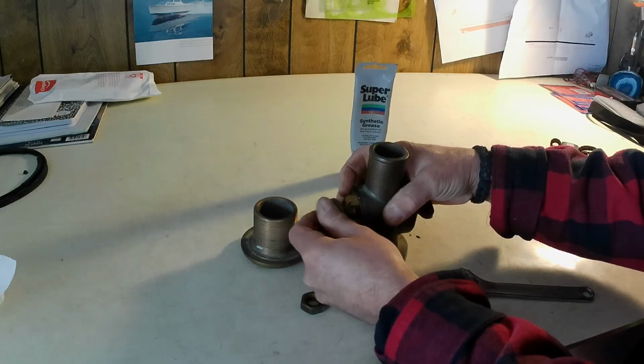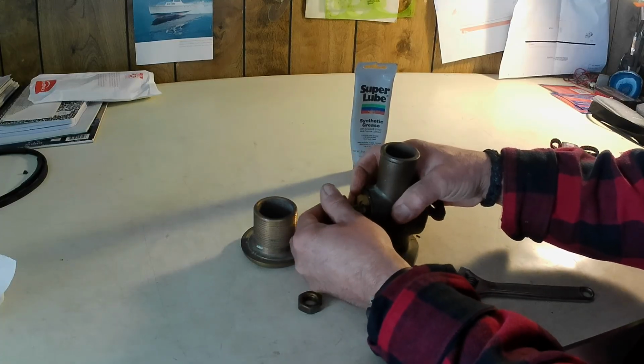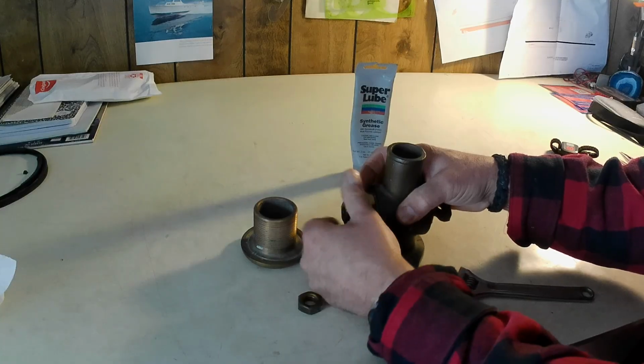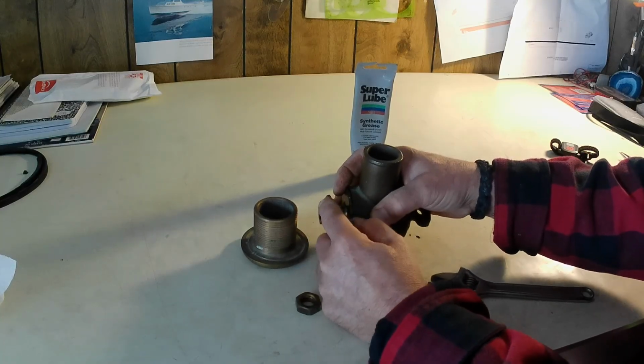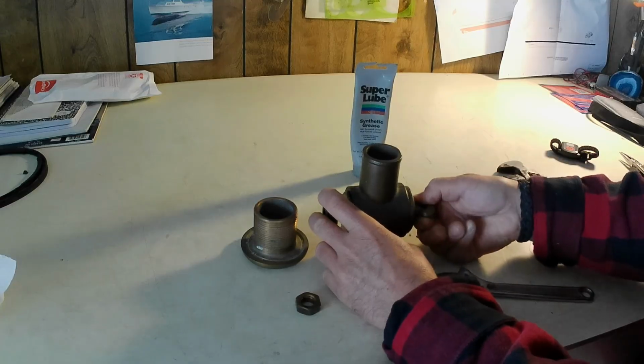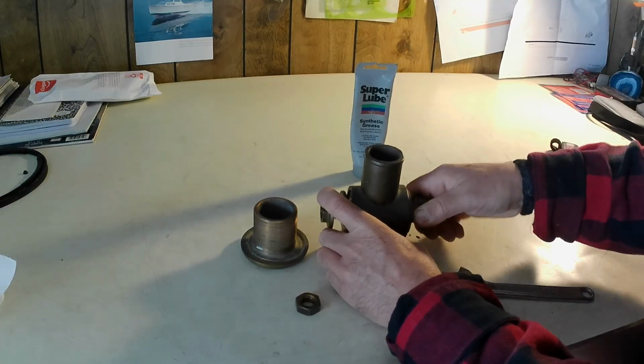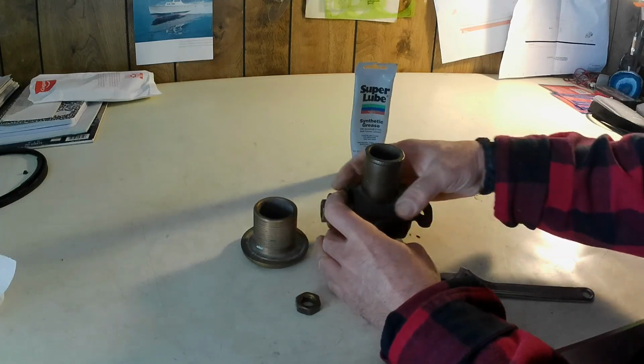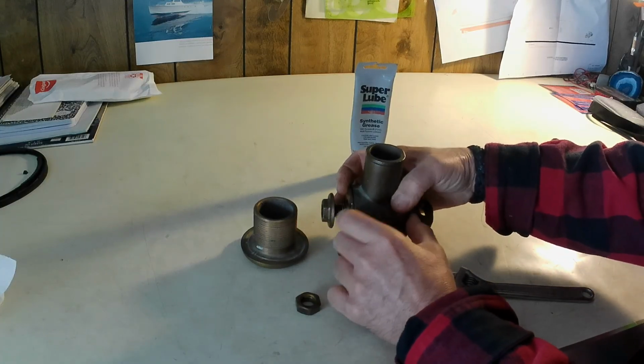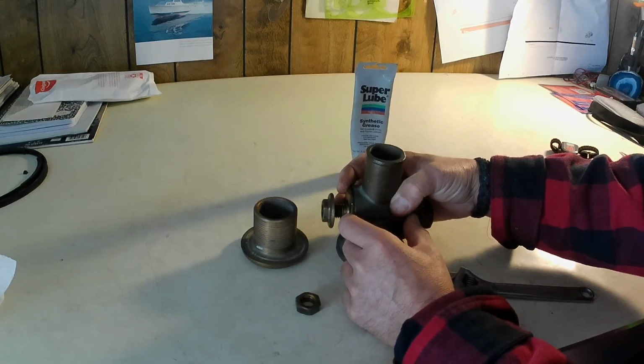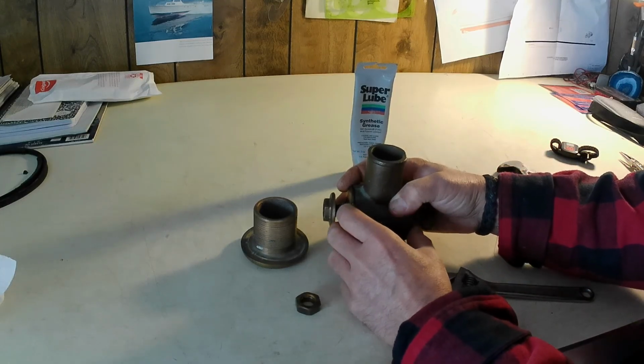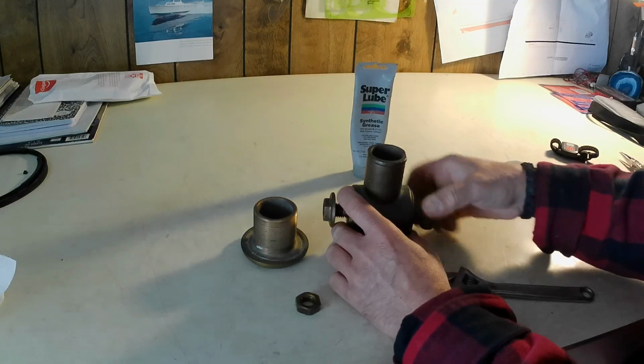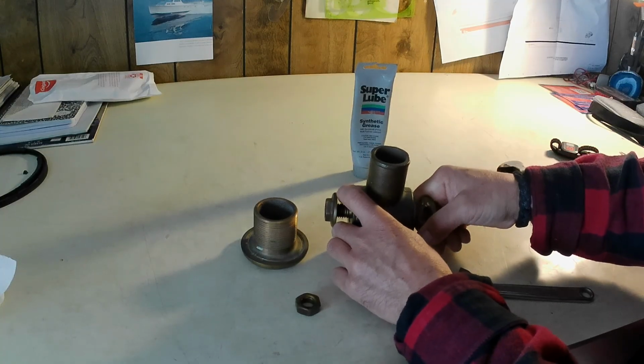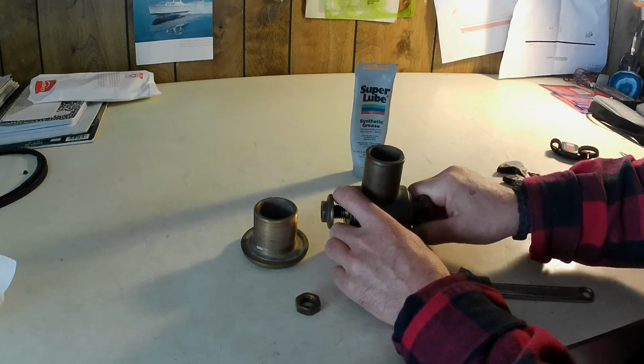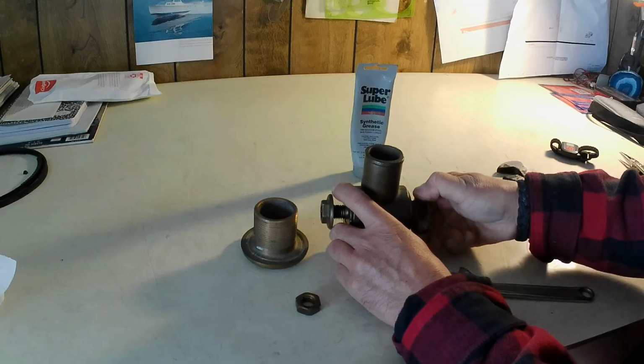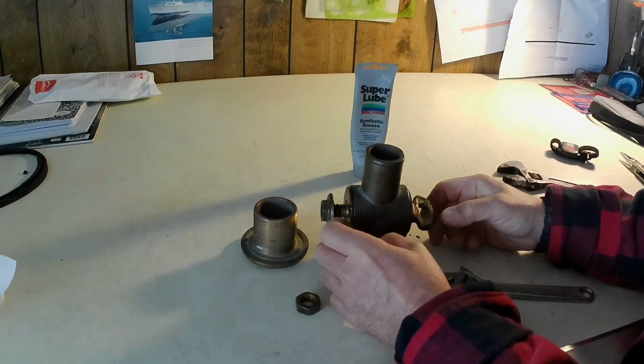The reason there's an art to it is if you reassemble this and immediately tighten this down so much that you cannot spin this plug relatively easily without a large tool, then what you'll have done is you'll have squeezed all the grease out. So this takes a little practice. What you've got to do is tighten that to just the right point so that this thing spins by hand but doesn't spin freely with vibration.